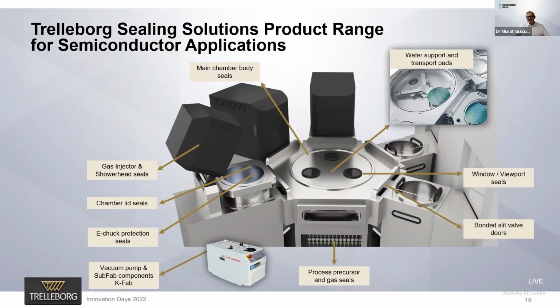So we can offer dynamic seals and static seals. They can be rotary, or just, for example, slit valve doors. We can offer slit valve doors as well. And for static seals, most of the examples are chamber seals and some gas seals. So we have quite high chemical resistance of our Isolast PureFab grade, so they can also be used for sealing process precursors and gas seals, especially for ALD and deposition applications. Inside the chamber, E-chuck protection is another important application for us, because the elastomers are very close to the wafers. Therefore, the contamination, purity, particulation is extremely important. But JPF10 and JPF30 can solve all these problems.